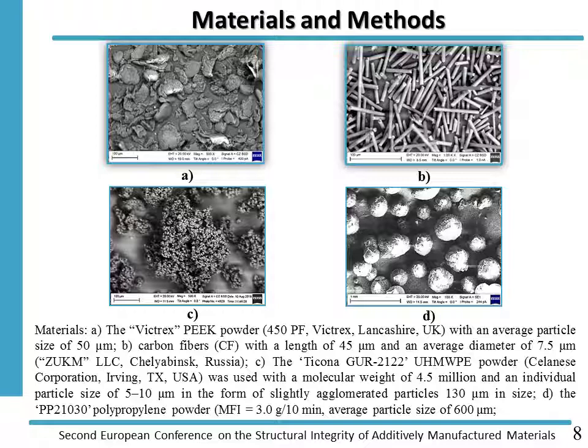Also we use the ultra-high molecular weight polyethylene powder produced by Celanese, with a molecular weight of 4.5 million. The individual particles were 5 to 10 micrometers in size, and those particles were slightly agglomerated. We also use a polypropylene powder with a rather high melt flow index in order to modify the ultra-high molecular weight polyethylene to provide flowability.